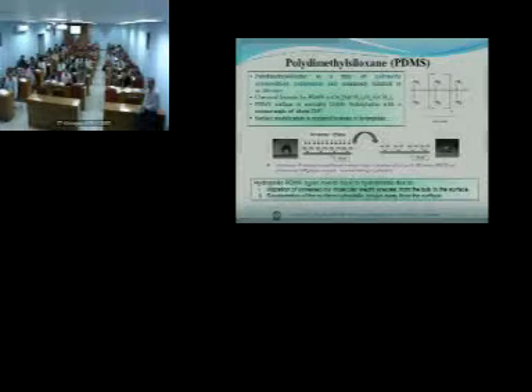So we started with PDMS, and let us say we use a PDMS layer. Over that we will have a nichrome heater by thin film deposition process and lithography process. But when we started, we first found that the surface of the PDMS is hydrophobic in nature. What does it mean? Hydrophobic means it will not hold water because of this CH3 bond. And as it is hydrophobic in nature, if I deposit a nichrome film over there, or any film, there will be an adhesion problem. It will not be compatible with MEMS fabrication. So this is the first problem we have faced.